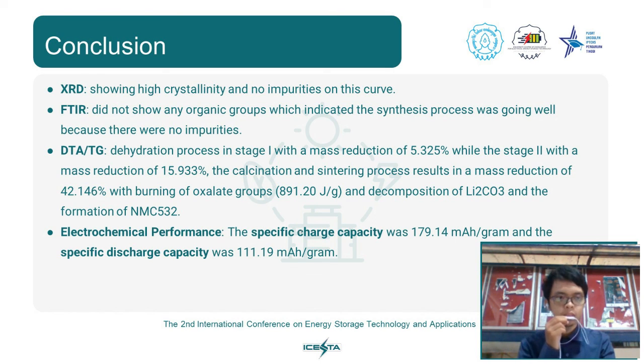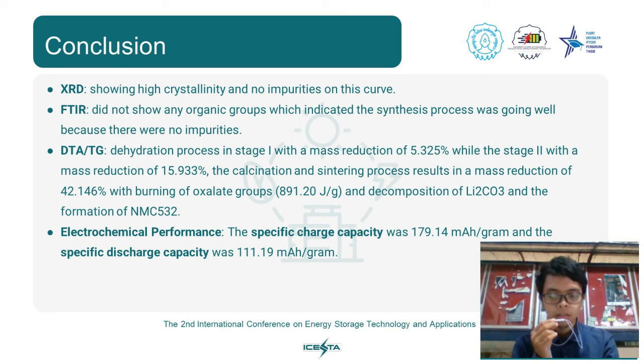The conclusion from our research: the XRD analysis of NMC532 shows high crystallinity and no impurities. Also, the FTIR test didn't show any organic groups, which indicated the process went well. And then, from the thermal gravimetry and differential thermal analysis tests, the dehydration process in stage 1 had a mass reduction of around 5%, while stage 2 had a mass reduction of around 15%.